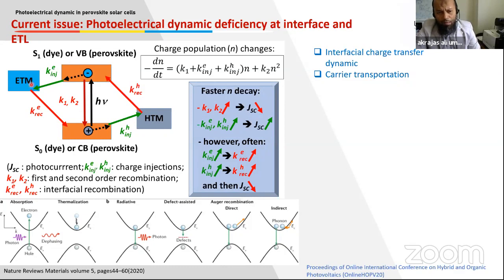Now let's say after the electron is injected here, the nature of the transport, the dynamics here, also strongly depends on the properties of this material. When the transport is smooth, electrons easily transport to the external circuit for photocurrent. If the transport does not occur normally, they will accumulate at the surface. Again, this will trigger recombination at the interface, and we may lose again the precious current we expect from the